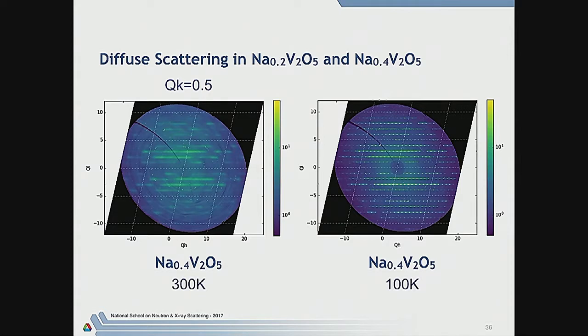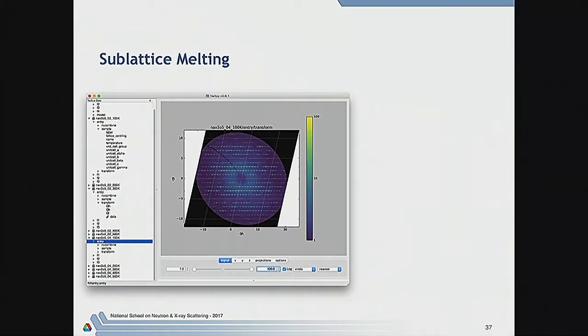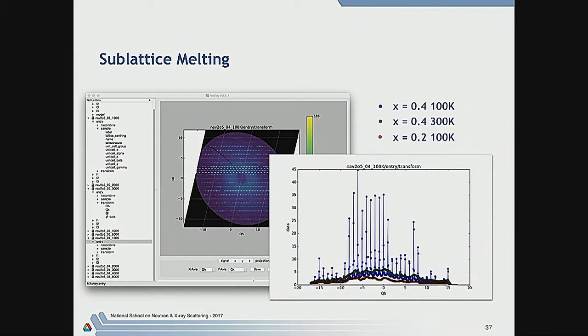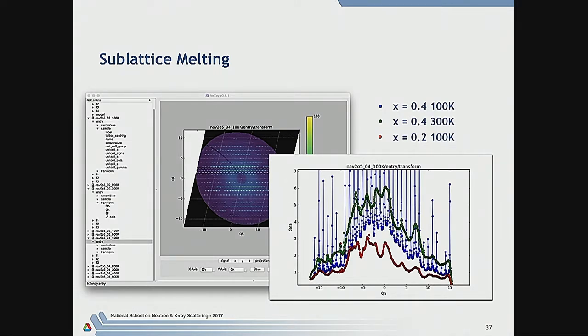Okay. So here the sodium sublattice is completely disordered, or at least only short-range correlated. Here there's actually a degree of long-range order within that sodium sublattice, as shown by the existence of Bragg peaks along this crystal. So how do you model this? Well, in Q-space, it's really complicated, okay? So the green represents the high temperature structure. You can see these rods have a very strong Q dependence. It's very complex. We know because they're rods that they represent roughly two-dimensional disorder. In other words, it's correlations of the sodium ions within the ladder plane. And we can infer some other things, but anyway, this is quite complicated. And then at low temperature, superimposed on that, some of this intensity goes into these Bragg peaks.